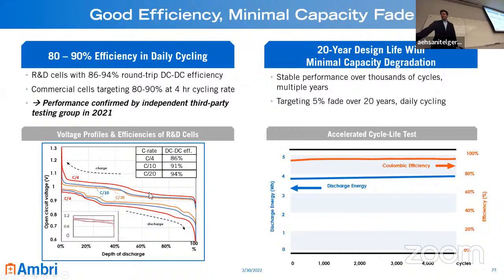But you can see here the C/4 batteries, red lines, are furthest apart. This is the most overpotential, so the charge and discharge voltage profiles are separated the most. And then the 10-hour and 20 hours are closest, because as we discharge more slowly, there's less voltage drop in the battery. So the round trip efficiency goes up. So it's easy to go slower in our battery and most batteries. And as we go faster and faster, the efficiency starts dropping off. So the main reason we're not looking at 1 hour or 2 hour applications is because then the efficiency starts getting worse and worse. And then here's some accelerated cycle life testing up to close to 5,000 cycles, showing no capacity fade over this period. And we're targeting a 5% fade over 20 years of daily cycling.